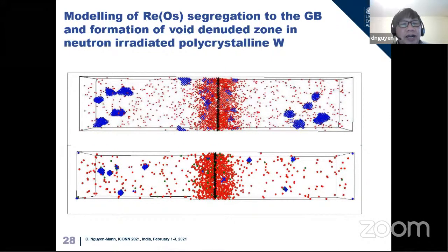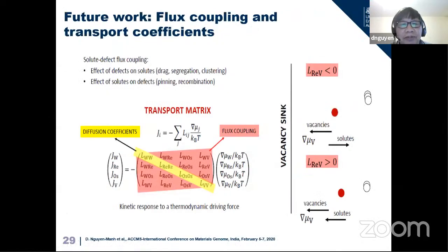One of the last slides shows that we can also model the segregation of rhenium and osmium to the grain boundary, whereas the void is segregated away from the grain boundary. So it demonstrates that the model can also predict the denuded zone in the polycrystalline tungsten sample.